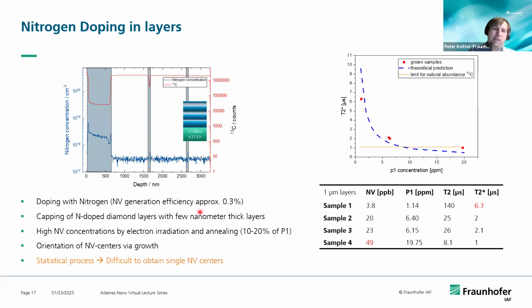Another thing that we have with layers is we can add an additional capping on top. And yeah, as you've seen, for the bulk substrates, we can also do this for layers. 10 to 20% of P1 can be converted to NV centers by additional electron irradiation and annealing treatments.